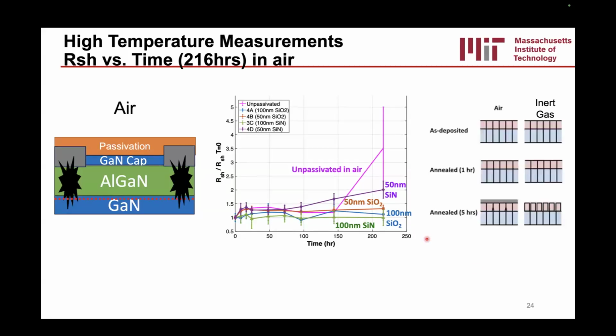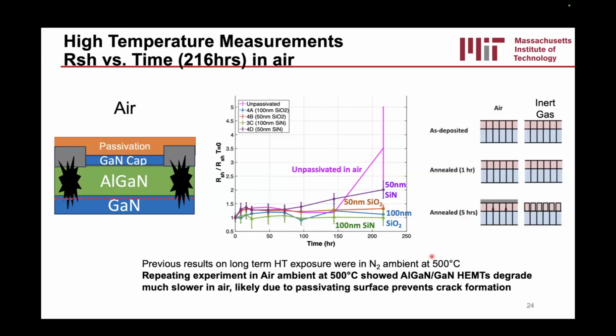The reason for this, we suspect, is that in air, there is an equivalent passivation layer because the sample gets oxidized. However, in an inert environment, the sample is not passivated. And so there's a lot of surface states, a lot of dangling bonds, and we suspect that cracks are forming, those bumps you saw in the AFM are forming from those surface states. And that's what's leading to the degradation. And so we find that these devices degrade much slower in air than in an inert environment, which is kind of the opposite of what you'd expect for a typical chemistry experiment.